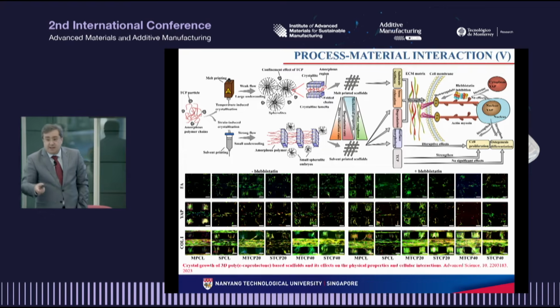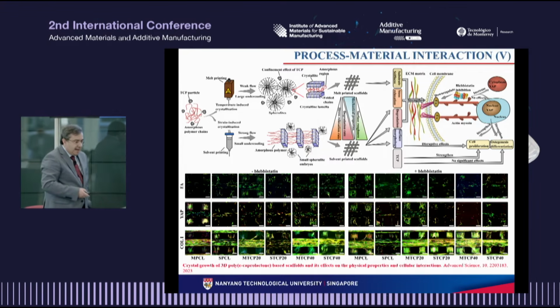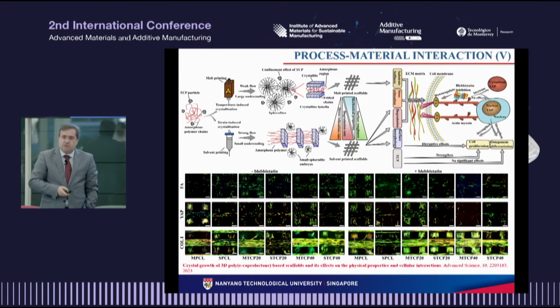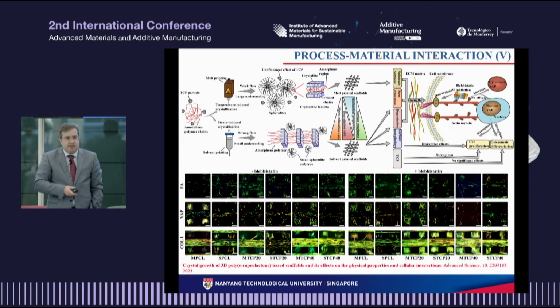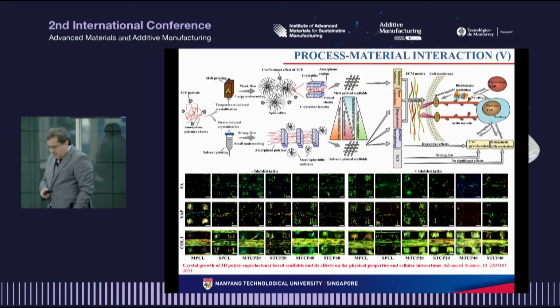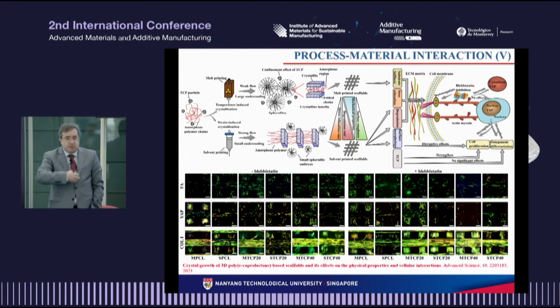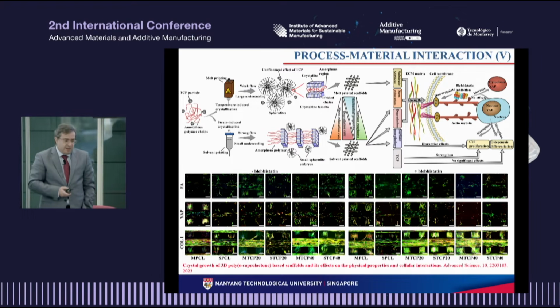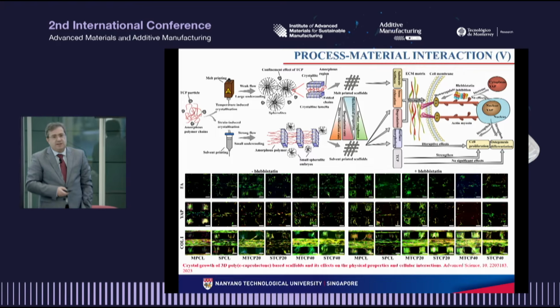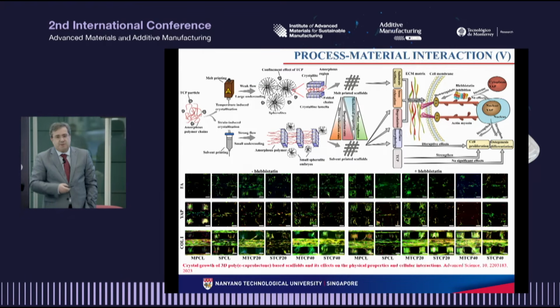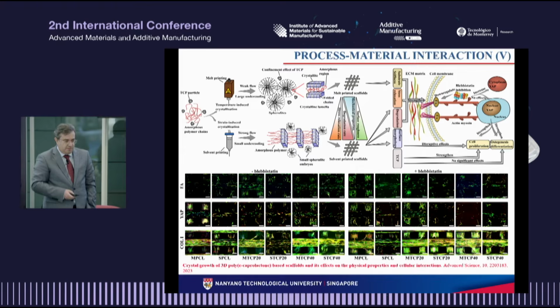So we created an ink using dichloromethane. And this process was characterized by a strain-induced crystallization, leading to the formation of relatively small and fragmented lamella-like structures and shish-kebab crystals. And as a consequence of this different microstructure, we printed scaffolds with the same geometrical characteristics, but totally different properties, biological properties, physicochemical properties.